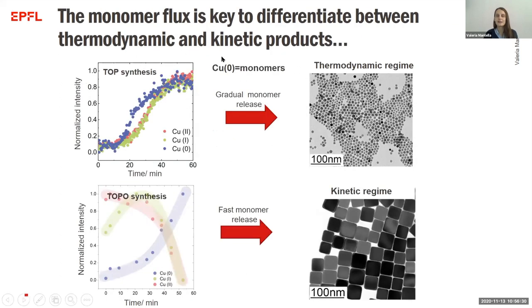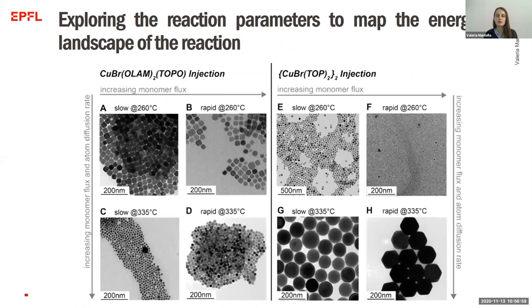So if now we identify the copper zero species as the monomers, what we learn is that a gradual monomer release, as obtained during the synthesis with TOP, will enable us to synthesize the most thermodynamically favored shape, which are spheres. Instead, a fast monomer release, as obtained during the synthesis with TOPO, will lead to kinetic products such as cubes in this case.